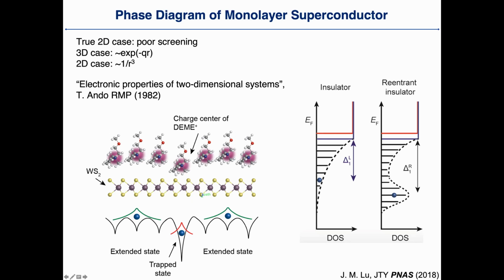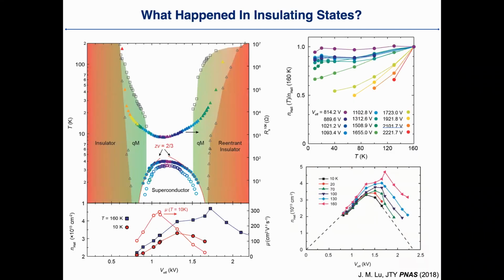So then we have two things. One is the ion gating is very, very isolated. You can isolate the electronic state in a monolayer. And the second message is that if you gate too much, the system again becomes insulating, and the electric field starts to penetrate, and the effect actually goes to the second layer. And if you don't have a second layer in this particular case, then you will have a very insulating state. And this actually explains why we have this dome.